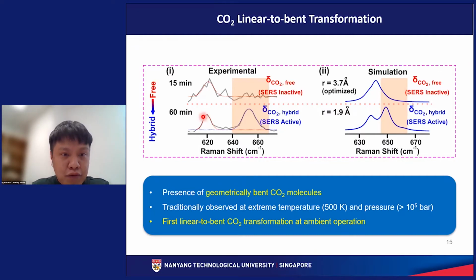However, upon flowing CO2 gas for 60 minutes, we can see an evolution of a peak around here, around 656 wave number. This is the region where the CO2 bending mode can be observed. The presence of a CO2 bending mode means that our initial linear CO2 is no longer linear. In other words, this must show that a CO2 with a bent geometry is present near our plasmonic nanoparticle surface. Using simulation, we are able to confirm this, whereby right now we are able to see the initially unobservable CO2 bending mode in our simulated SERS spectrum.